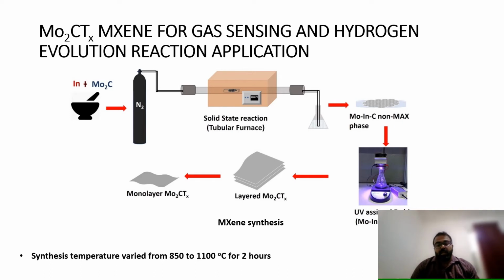The obtained non-MAX phases were used as the precursor for MXene synthesis. Here we use the non-MAX phase in phosphoric acid with the support of UV light, and this UV light serves as the catalyst for the reaction. We obtain a layered two-dimensional MXene after etching, followed by exfoliation in DI water with the help of ultrasonic waves, and we obtain two-dimensional Mo2C MXenes.